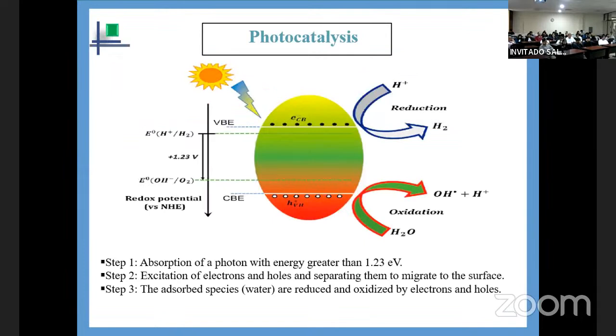The first step is to define the application and to search which conditions must be verified by the material. So in photocatalysis application, we are looking for a semiconductor whose valence band and conduction band edges must be localized between the redox potentials of water, and the band gap must be greater than this value. So an electron in the valence band can absorb visible light to move to the conduction band. And this excited electron is reduced in this reaction to produce hydrogen, and this hole is replaced by an electron released from oxidation.